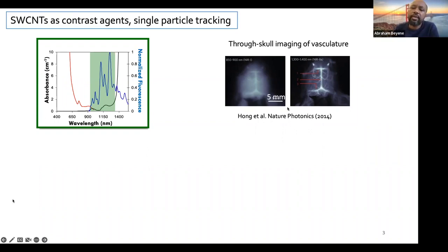And what is really striking for me, at least from this study, is a demonstration that the traditional NIR region of the spectrum in this 800 to 900 nanometer range really doesn't give you the type of signal to background ratio that proper shortwave infrared imaging does, which is around 1300 to 1400 nanometers. So you can see how, and trying to do this in the visible range of the spectrum is totally futile. You would not be able to see anything. But you can see how this study tries to really demonstrate the utility of imaging in this range of the spectrum and how it facilitates imaging in fairly complex and optically challenging preparations.